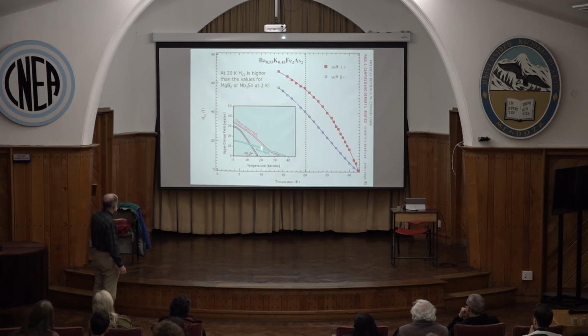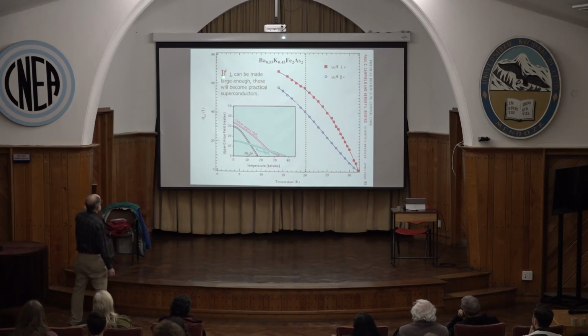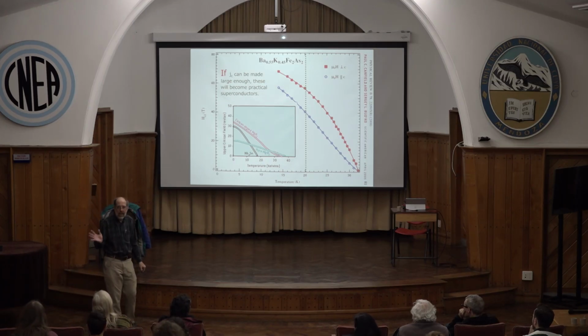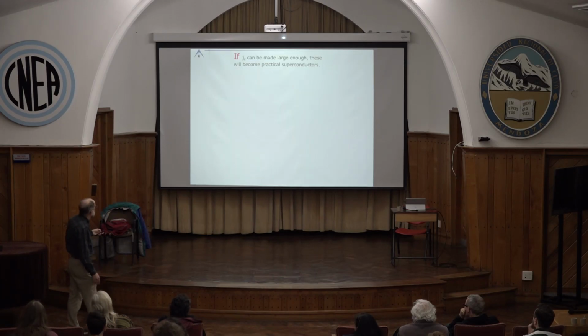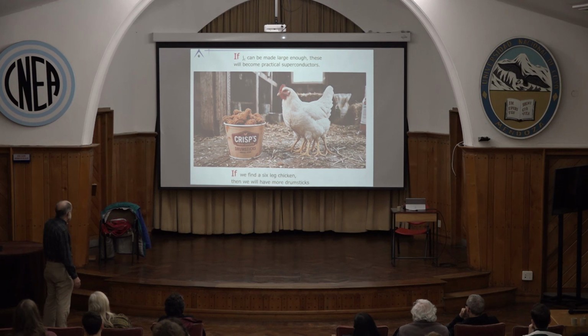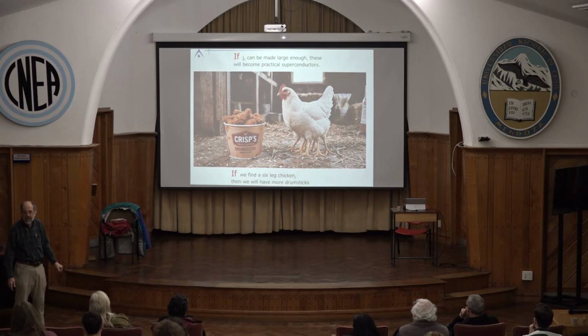Remember, MgB2 is used at 20 Kelvin, and this is about 15 Tesla. At 20 Kelvin, the upper HC2 is above 40 Tesla. Holy Moses! If JC can be made large enough, these will become practical superconductors. But remember what I said about JC. So if JC can be made large enough, these will become practical superconductors. If we have a 6-legged chicken, then there will be more drumsticks.